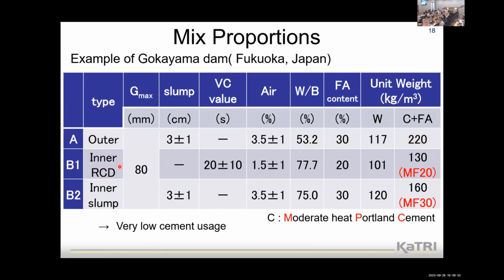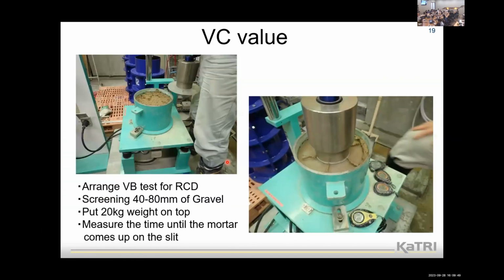And on the other hand, for RCD, the inner part of the concrete, 130 kilograms per cubic meter is used. And since it is no-slump concrete, we estimate the property by the VC value. What is the VC value? This slide shows the VC value, which is arranged as the VC test for RCD.